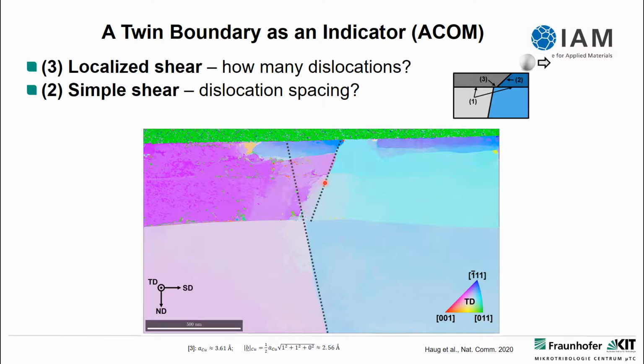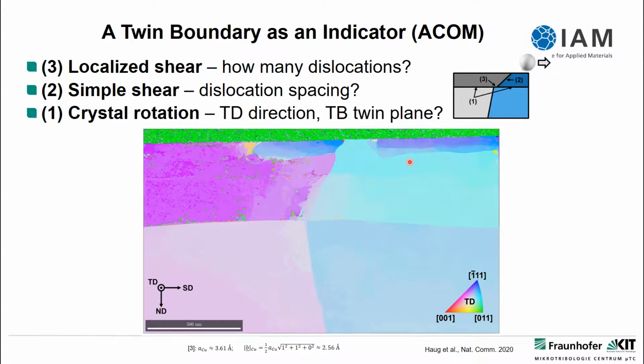We can see by how much we actually tilt, and then calculate how many of those, on which number of slip planes, we need a dislocation to move through. If we do this, we see it's roughly every other slip plane, every other lattice plane above the dislocation trace line, where we need to move a dislocation. And that makes sense, right? Every other one, kind of. So that kind of makes sense, and that's something one can imagine is happening.